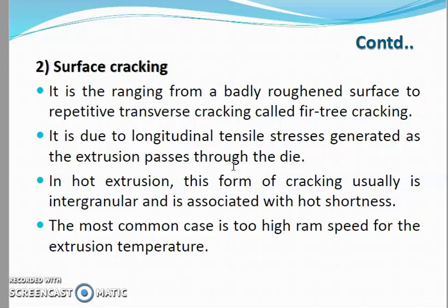If you see the reasons why surface cracking occurs, the primary cause of the surface cracking defect is excessive stress on the surface of the work material. Increased friction will create a more favorable environment for surface cracking. In hot extrusion, this form of cracking is usually intergranular and is associated with hot shortness. The most common cause is too high a ram speed for the extrusion temperature.